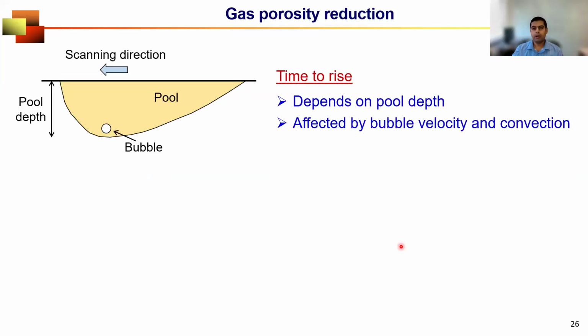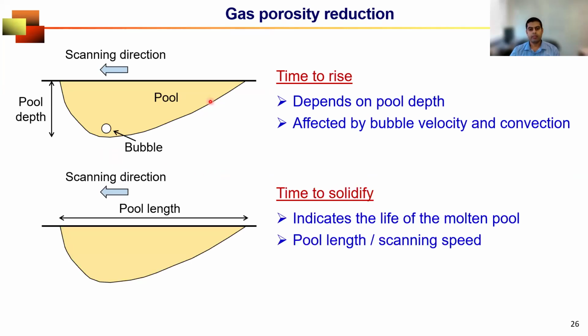So the other type of porosity is called gas porosity. Now, there are two times that are important, time to rise and time to solidify. What are they? Let's imagine this is the molten region and we have a gas bubble. Since the density of gas is less than the density of liquid, because of buoyancy, this gas bubble will try to float up, rise up. Now, before it can rise up and escape from the molten pool, if the molten pool solidifies, then it will be trapped and cause porosity.